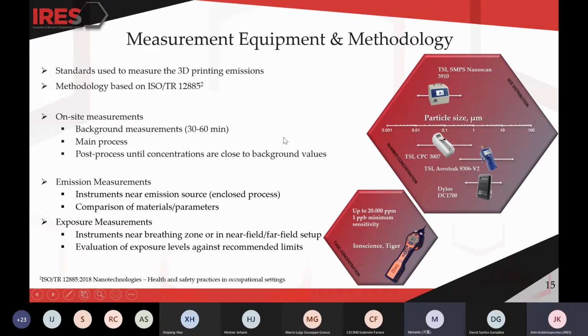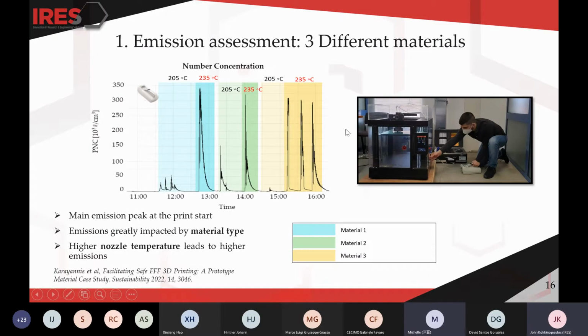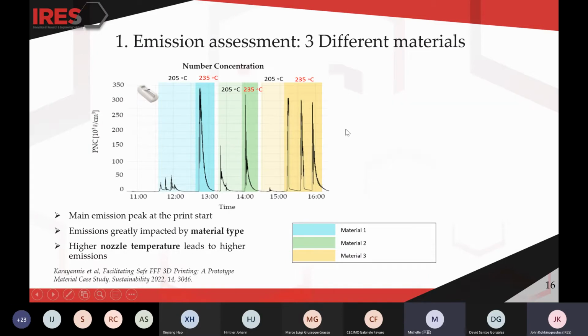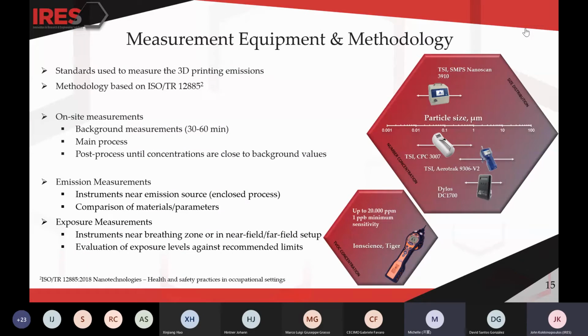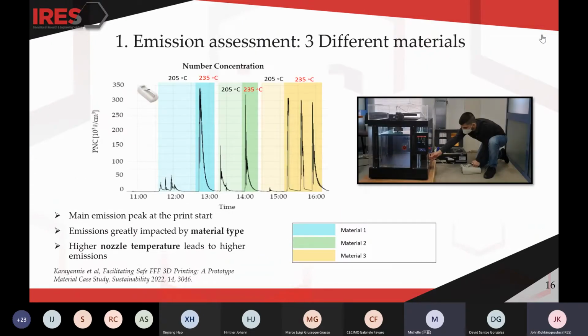In the previous slide, I'm sorry, in this slide you can see the equipment that we use in the picture. Exposure campaigns were performed using these instruments that enable the measurement of number concentration for particles between 10 nanometers and 25 micrometers, size distribution from 10 nanometers to 420 nanometers, and total VOC concentrations. And in the next slides, we will explore some results of various exposure campaigns with a focus particularly on ultrafine particles.